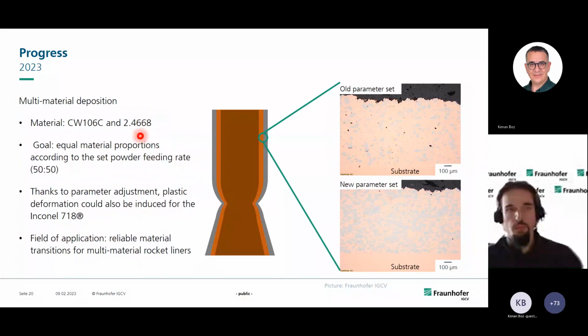Here we have a multi-material deposition of copper chrome zirconium and alloy 718 with the field of application, yeah, we want to fabricate a rocket liner. And what was the first goal for that? We wanted equal material proportions. As I've shown you before, we got 2 powder feeders, and these are volumetric powder feeders. If I, for example, set a feeding speed of 2 RPM for both of those powder feeders, I actually, of course, want nearly the same amount of powder of both materials in my final part.